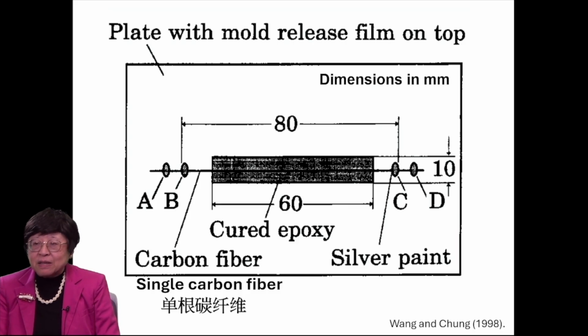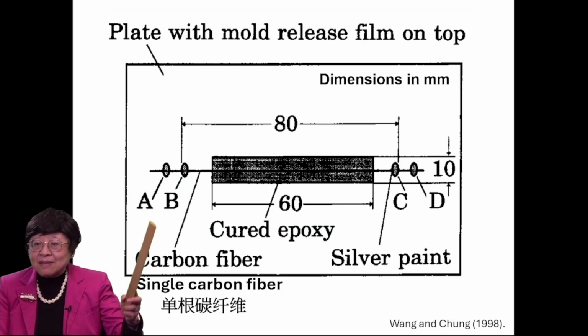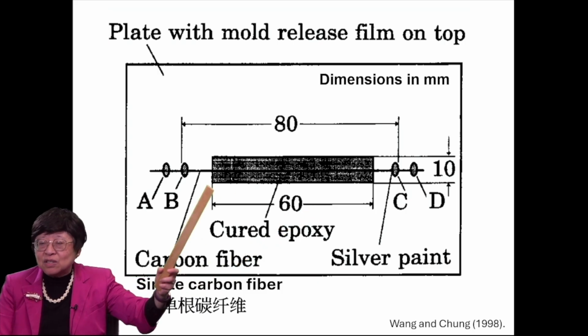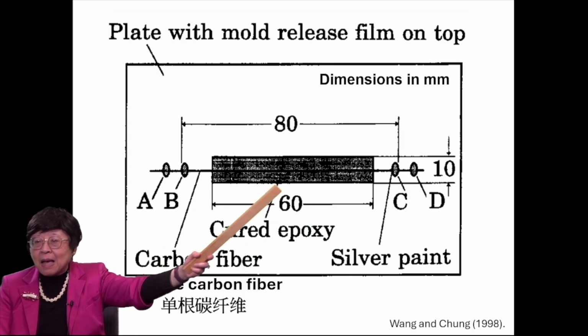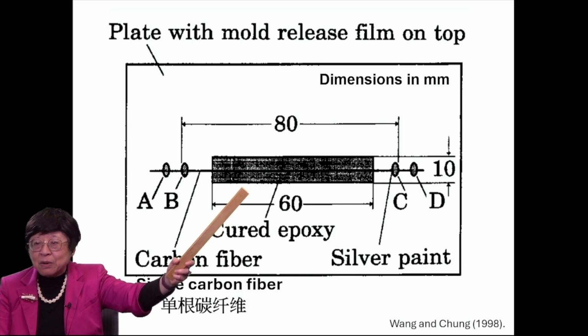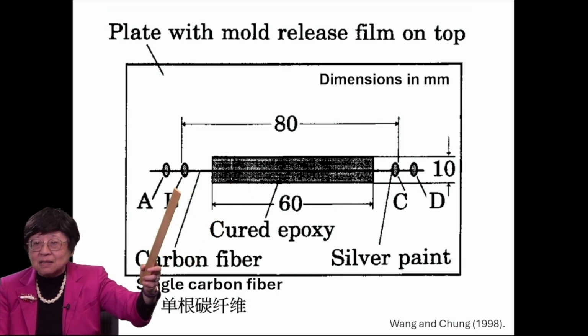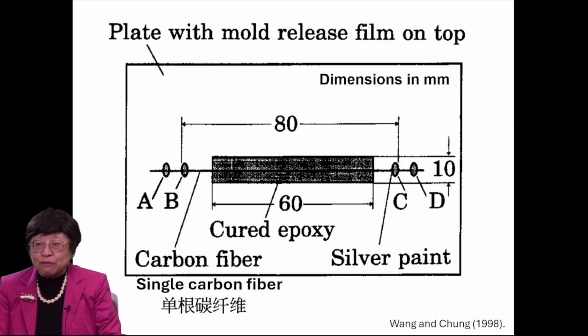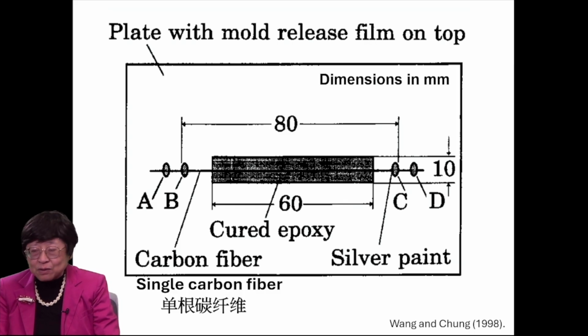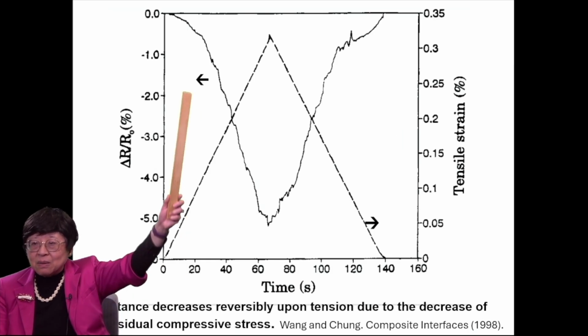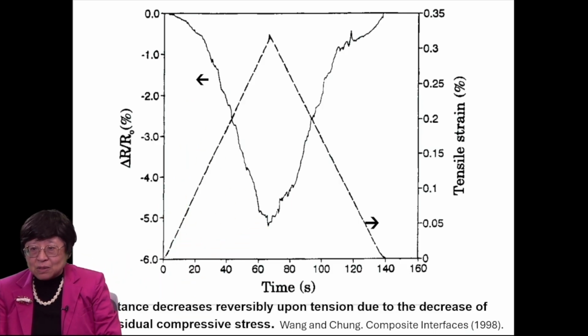Therefore, if after the fabrication you apply tension to the carbon fiber, you would cancel off that residual compressive stress, and that causes the resistance to go down. We measure the resistance of a single carbon fiber embedded in the middle with epoxy that has been cured. I have 4 electrical contacts labeled A, B, C, D to apply the 4-probe method to measure the resistance of this single carbon fiber. As tension is applied, the residual compressive stress becomes canceled and the resistance goes down. So indeed, that's what we observe, and it's reversible.